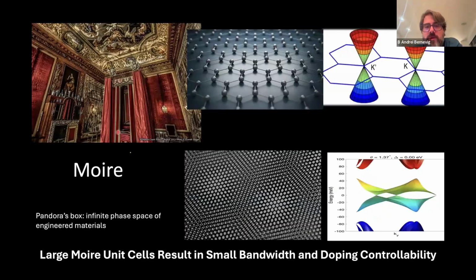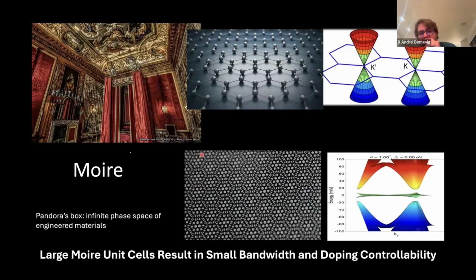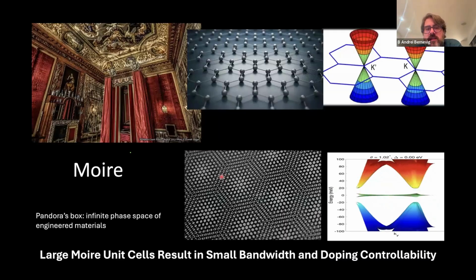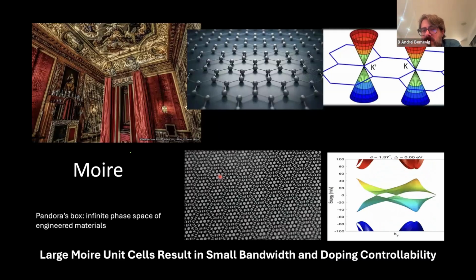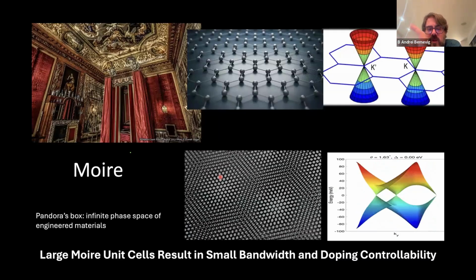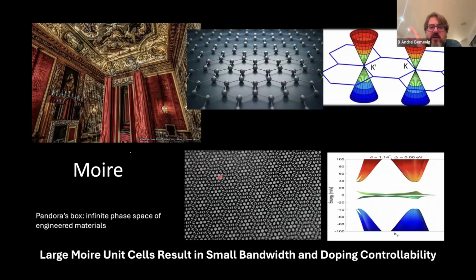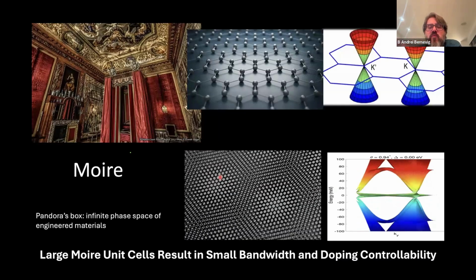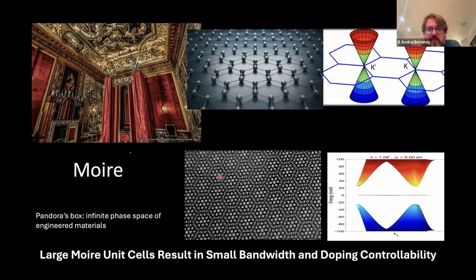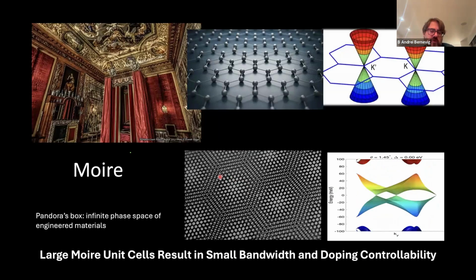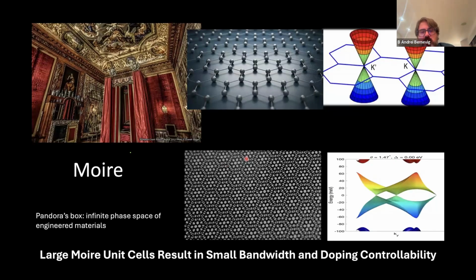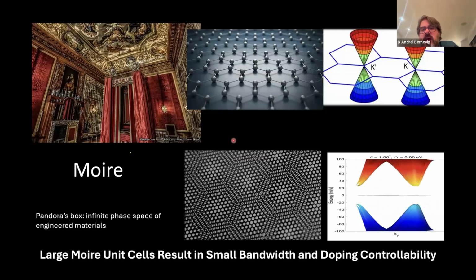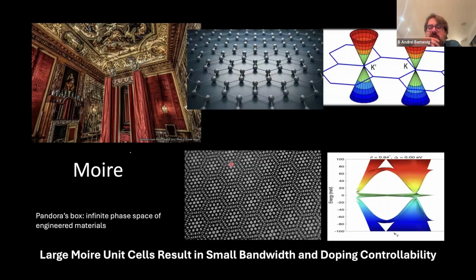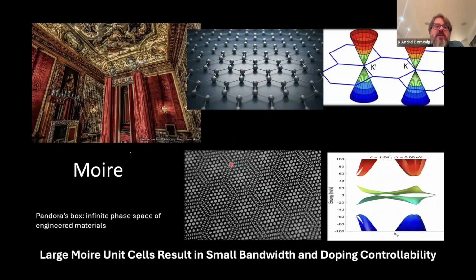So this is where Moire comes in, and this is really kind of like the alchemy of today. So the Moire field is basically creating bands with large interactions, but without having a spaghetti of bands. So they're very clean, or at least much cleaner than in 3 dimensions, where there's many other bands. And there's even an added advantage, you can manipulate them.